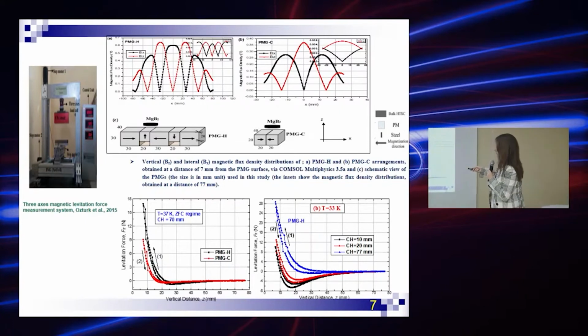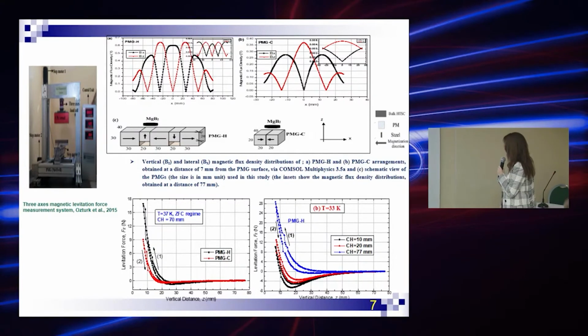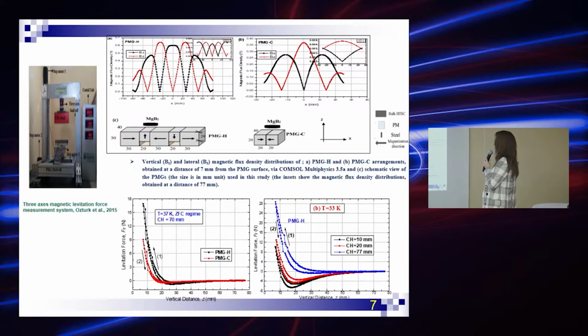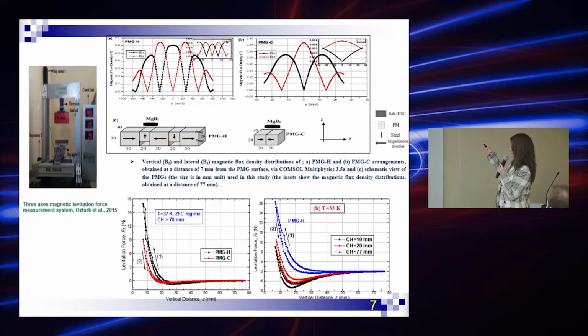And this figure shows the vertical levitation force versus vertical displacement, and the maximum levitation force value is higher for PMG Halbach compared to conventional, and this is in the zero field regime and the cooling height we chose is 70 millimeter, and it is due to magnetic flux distribution, because in the Halbach type, the Bx and Bz values are bigger.